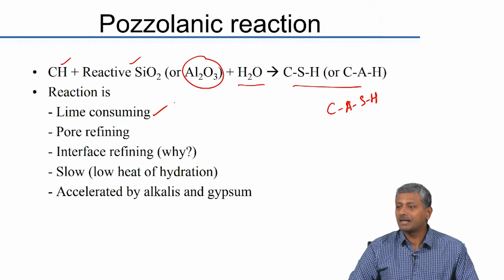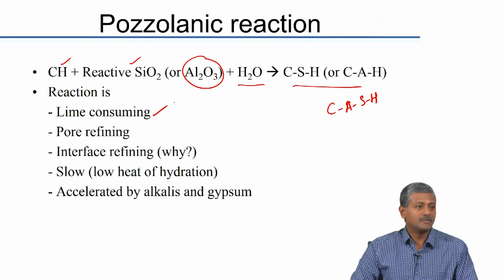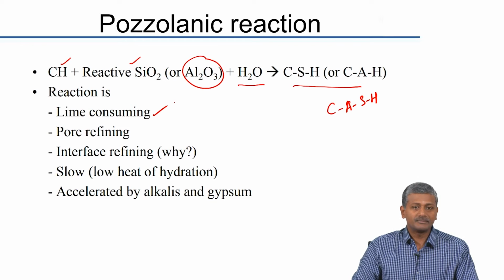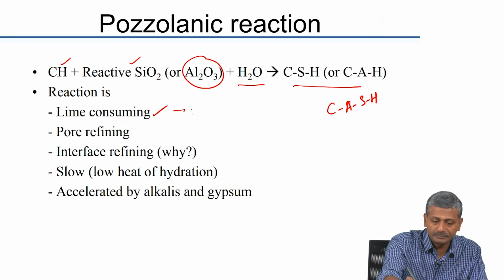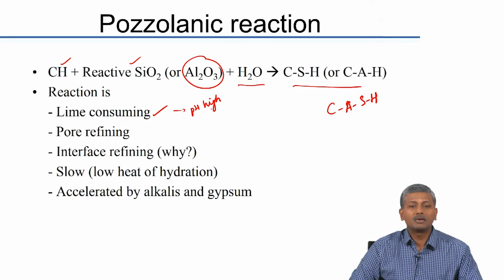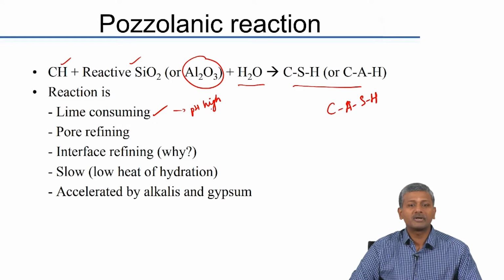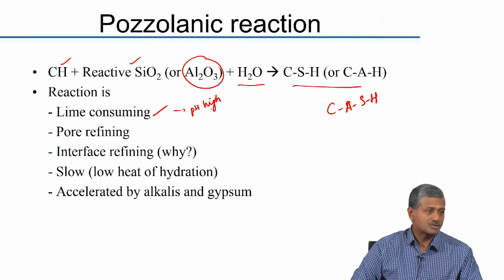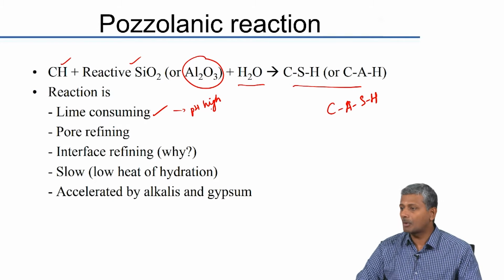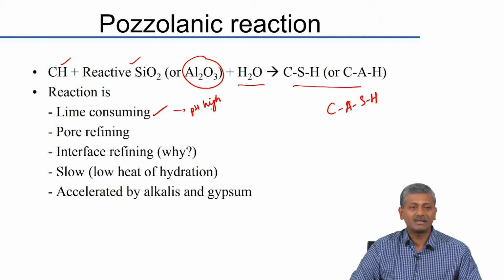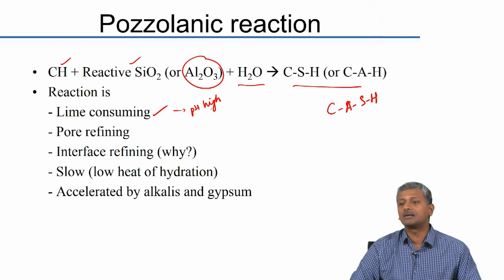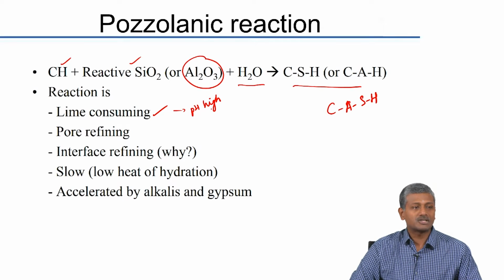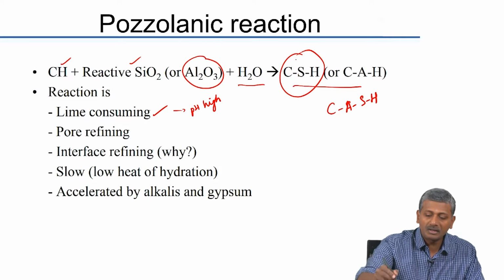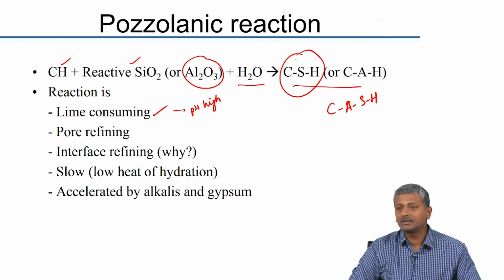We earlier said that lime, although it is good for the cement system, why is lime good for the cement system? It keeps pH at a high level. Lime keeps pH at a high level, right. It also is a solid crystal and it occupies the pore, because of which obviously it is contributing to the strength also. But the problem with lime is obviously that it gets reacted very fast when there is an external attacking species like a chloride or a sulphate, okay. So, if you can convert calcium hydroxide into a more stable material like CSH, you will not have that issue, okay.